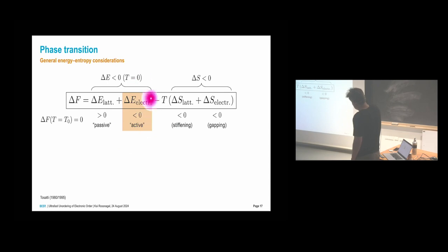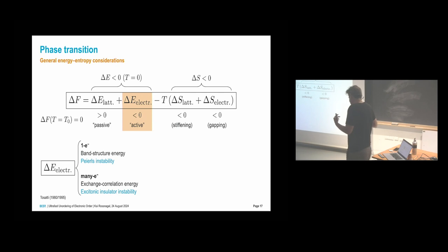This is the thing which drives the charge density wave formation, and there we can now discriminate two different types of instability. One is the well-known Peierls instability, where you have a single electron picture, and this is mostly band energy gain, that by gapping you get band energy gain. But then you can also see this as an excitonic insulator instability, where you see it as a many-body problem, and where your exchange correlation energy and the change in that drives this type of transition.